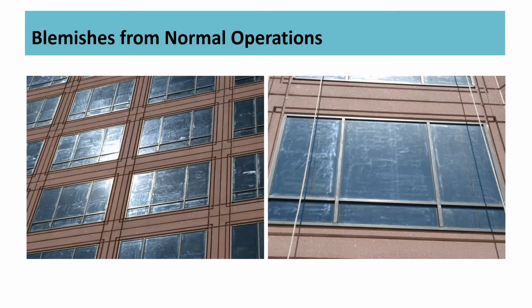Then, in an effort to try to remove such water spots from the glass, this is a project where an owner-developer hired a cleaning contractor to remove those water spots. What they ended up using was a proprietary glass cleaning material that contains silica, which we all know is a component of glass, has the same hardness of glass. They used that material on the end of a handheld polisher, and you can see the overall pattern that they used as they were going across the surface of the glass.